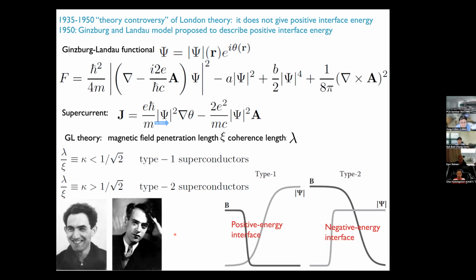So there are two fundamental length scales in superconductors, and depending on the ratio, they calculated that if there's some dividing value of 1 over square root of 2, then if the ratio of these two fundamental length scales is smaller than this, in type 1 superconductors, these domains want to be as large as possible, or preferably the system should have a monodomain.